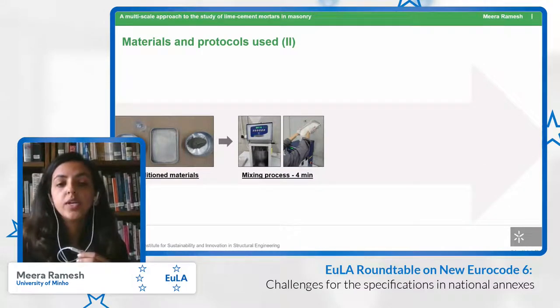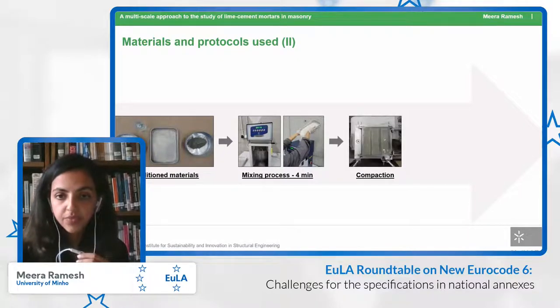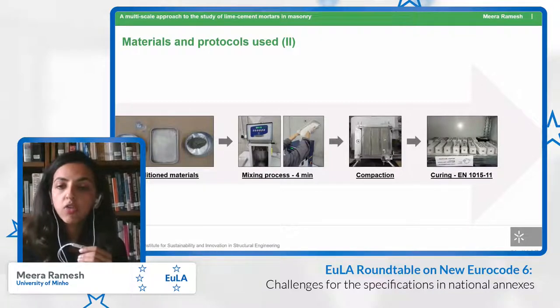The mixing process that we adopted was according to EN196-1, which has 4 minutes of mixing, including high speed and low speed, and all the mortars were prepared according to the same protocol. The compaction was done such that the mold was first half filled and jolted for 60 seconds, then it was completely filled and jolted again for 60 seconds. And finally, the curing of all mortars was done according to EN 1015-11, which recommends curing in 95% humidity for the first 7 days, and thereafter in 65% humidity.